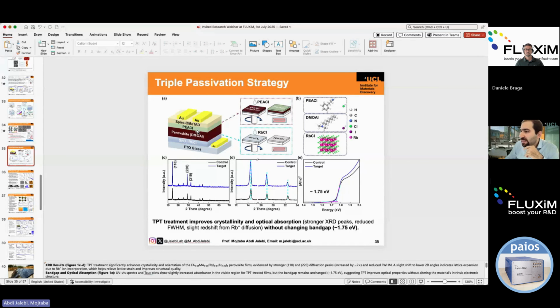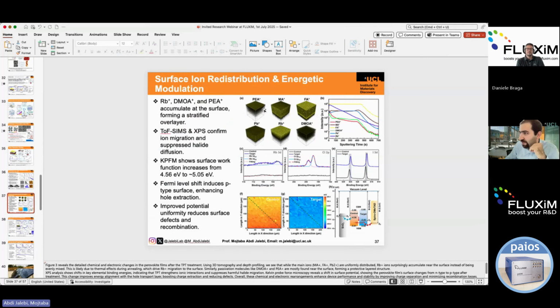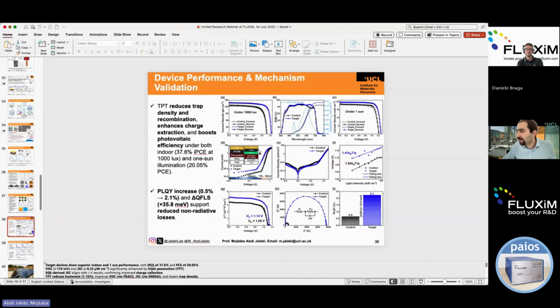And finally, the PEACl, another chloride-based passivation material on top, is helping us to passivate the defects at the top surface specifically. And again, the PEACl as well has a high concentration at the HTL side. So that was the reason, and it works not only for indoor but also for the one-sun wide bandgap perovskite, which is good for the tandem architecture as well. So basically, it works for both.